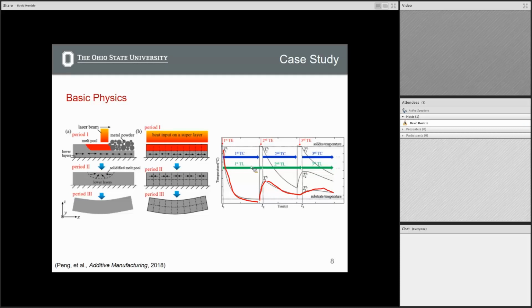So looking at this graph, we see that once we apply layer 2 and layer 2 begins to be reheated by layer 3 being applied, its peak temperature is above the reheating of layer 1 compared to layer 2. Is that due to a buildup of heat, as we talked about, with each layer? Exactly. So what's below it, you can think of it almost as a new boundary condition, right? Okay. And that's at a hotter temperature than the substrate temperature.